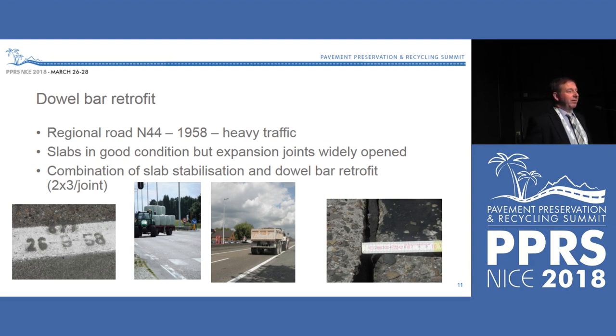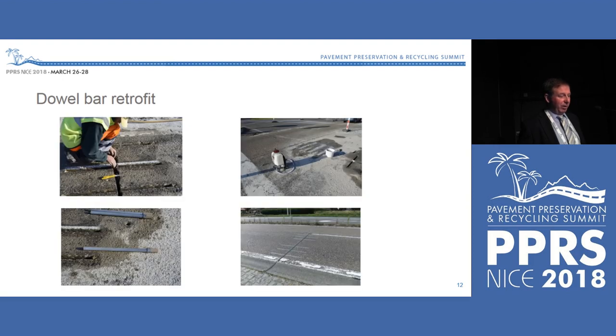So only a very limited number of slabs were cracked. But as you can see, those expansion joints that were used between those long slabs, they are widely opened, and they create problems in terms of comfort and problems of vibrations. So this was a good case to test the dowel bar retrofit, where you can see that they cut slots in the concrete pavements, and they insert the dowels manually, and the slots are filled again with a polymer modified cement mortar. As you can see on the picture on right bottom, we use 2 times 3 dowels, so exactly located in the wheel tracks.